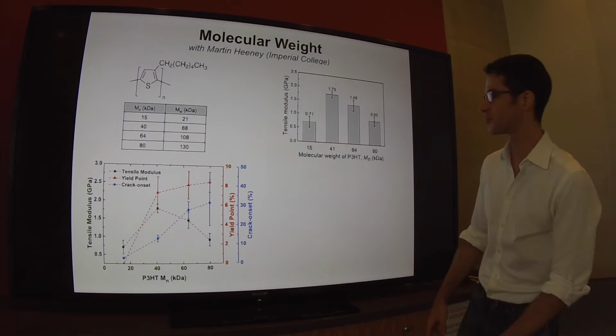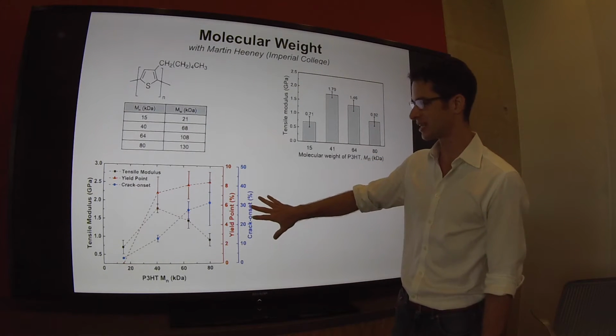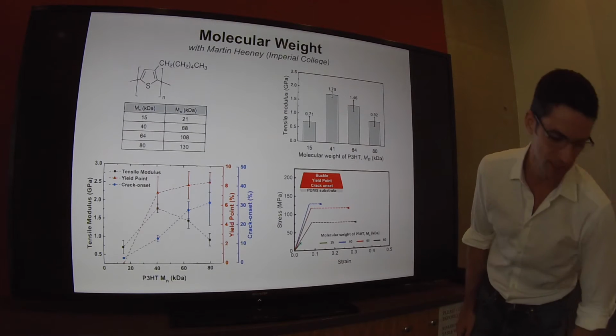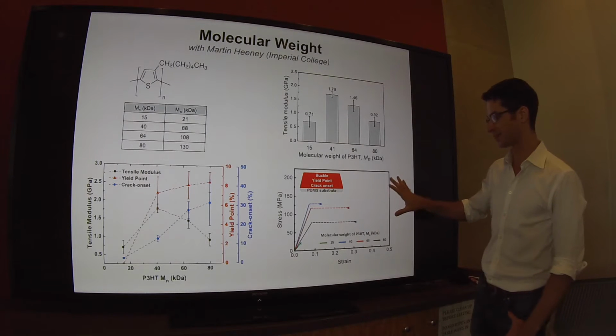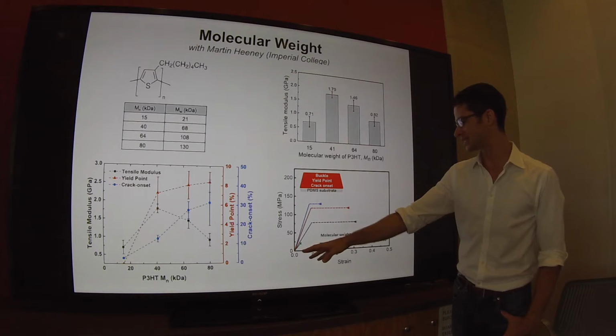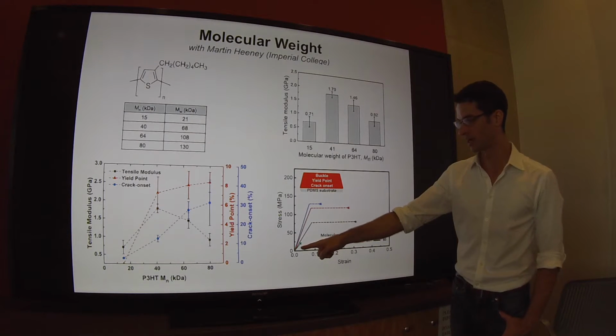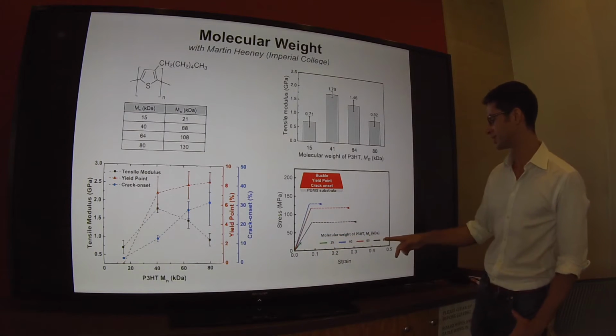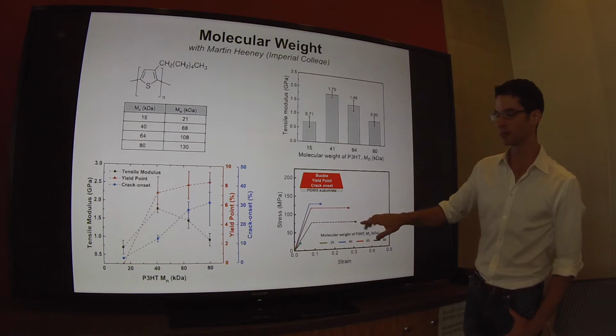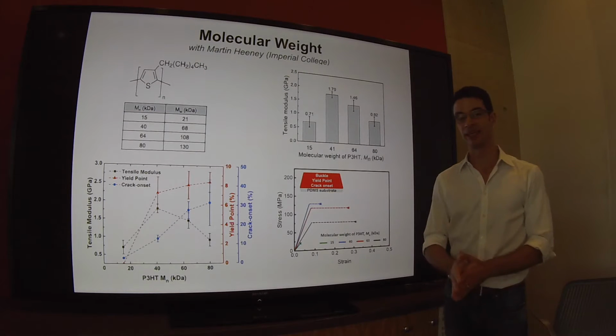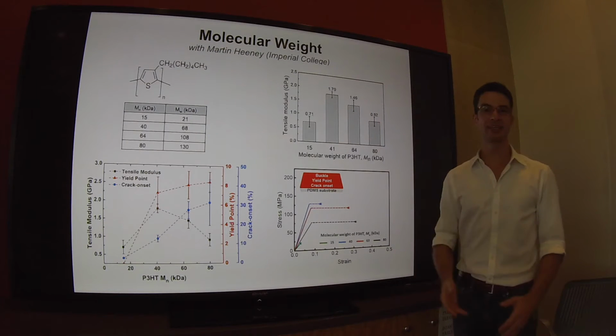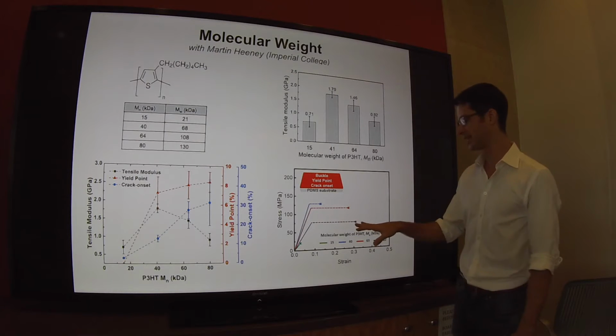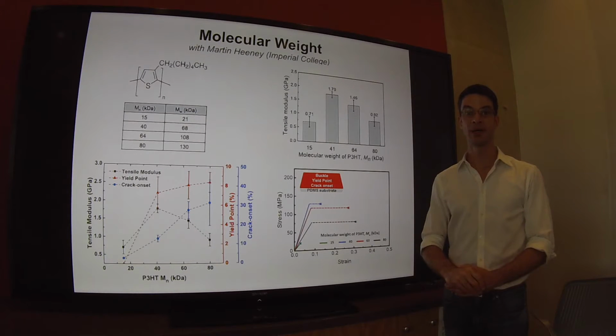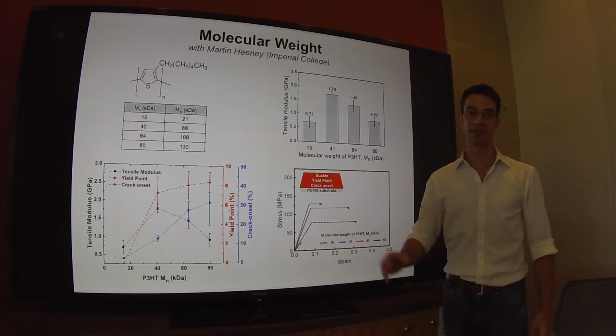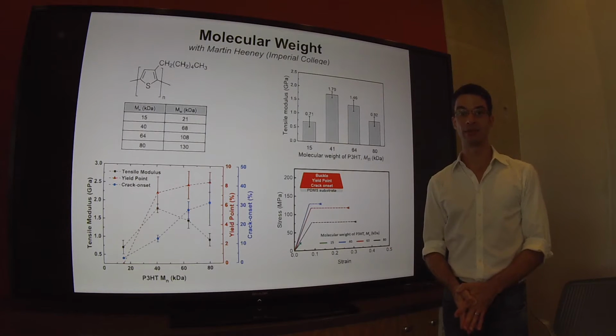So what you could do is plot the tensile modulus, the yield point, and the crack onset strain in this sort of confusing way, or you could convert it to a plot that looks sort of like a conventional pull test. So we see low molecular weight stuff has a low modulus, low crack onset strain, low toughness, and low resilience. As you increase the molecular weight, you're able to stretch the material out more and increase the deformability. Okay, so that's kind of an intuitive answer that we know from the engineering plastics community of the effect of molecular weight on the mechanical properties.